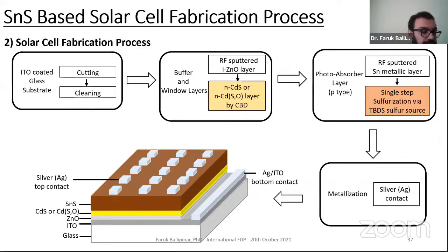After this, moving to solar cell fabrication. As I said, we use the superstrate solar cell device structure. The ITO coated glass substrate is cut and cleaned, and then the second step is the buffer and window layer deposition. First, as an intrinsic layer, RF sputtered zinc oxide, and then the N-type layer. There are two films, cadmium sulfide and cadmium oxysulfide. The third step is processing the P-type photoabsorber semiconductor layer. Again, first RF sputter the metallic layer and sulfurize through the TBDS source. After that, silver evaporation contact on the top of the device.